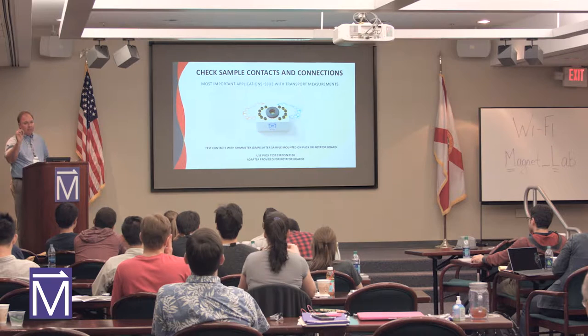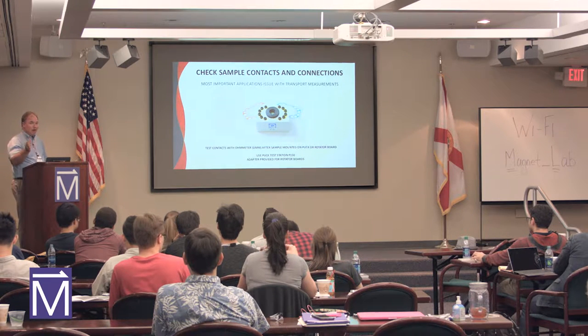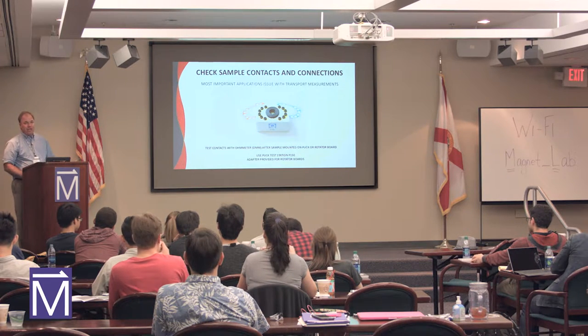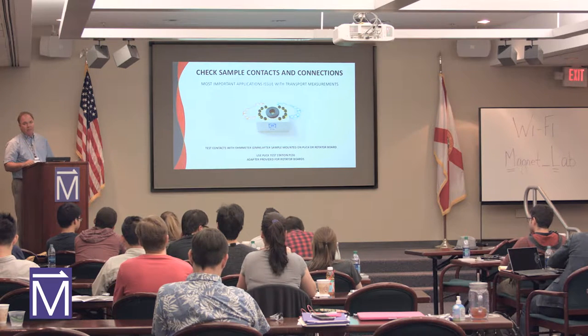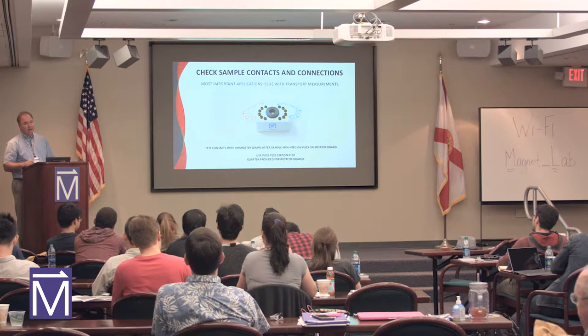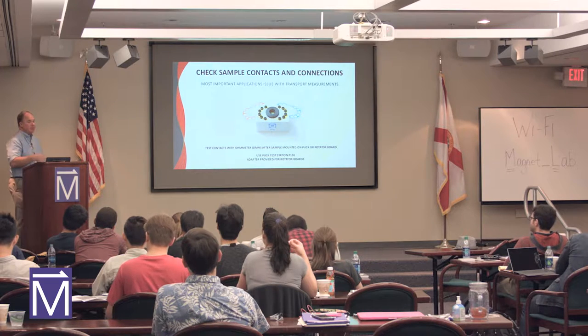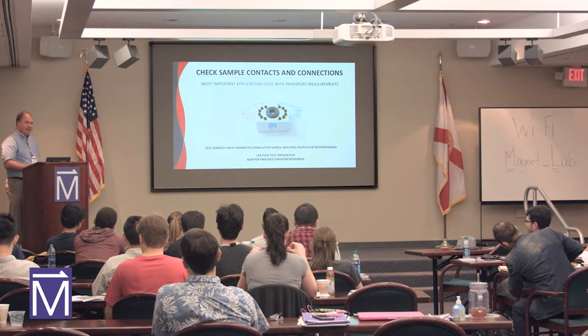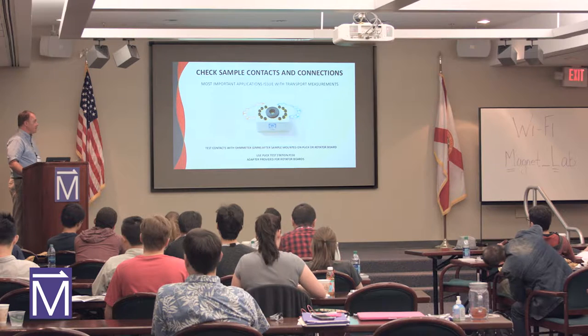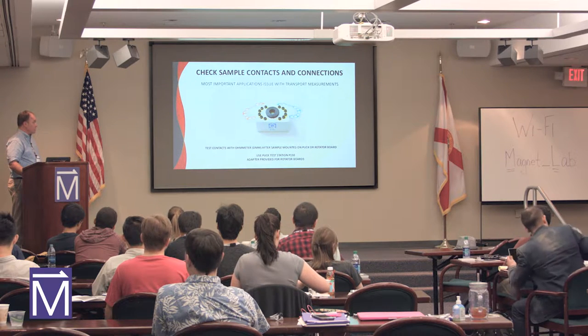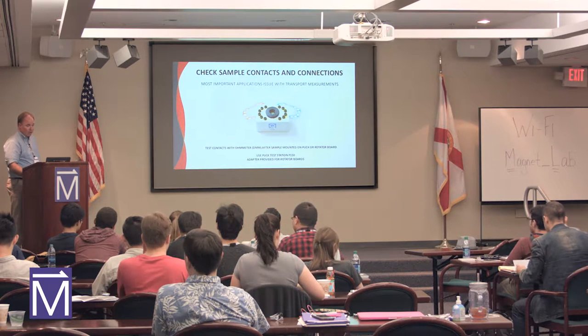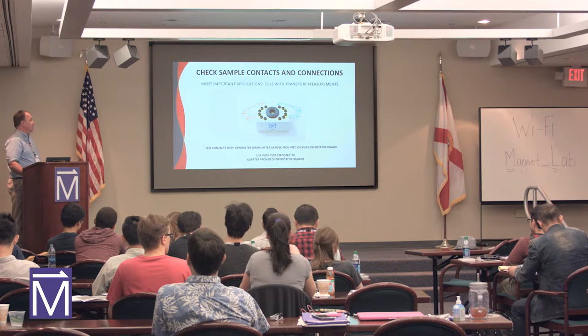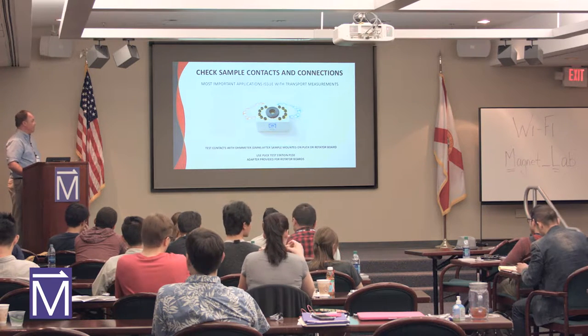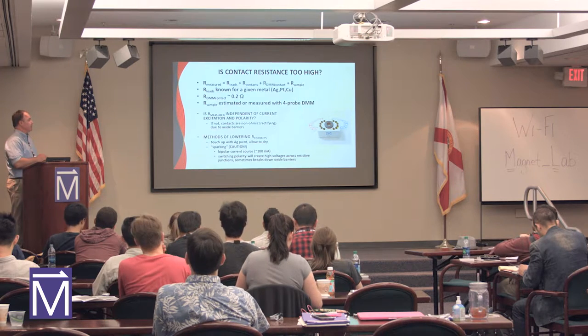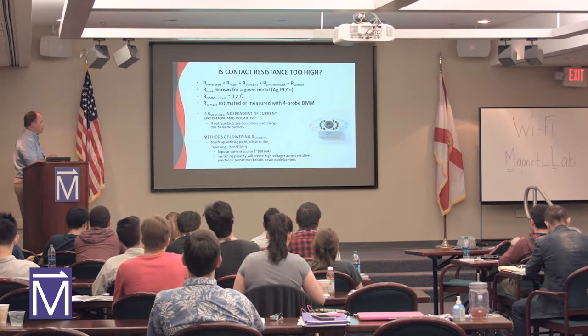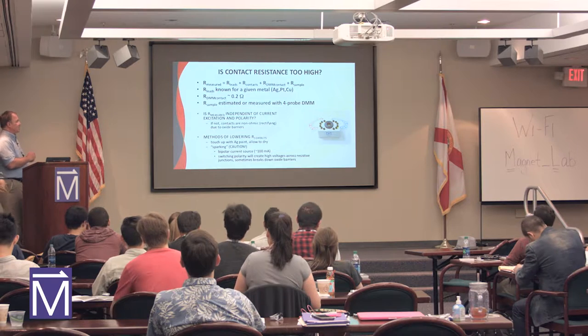So mount your sample on the puck, put it in the measurement jig, and then you can use an ohm meter, multimeter, or Keithley meter to make your electrical contacts at room temperature. Do you have good contacts? And then you can move it into the system. So we give you little kits depending upon the experiment. And if you have the rotator board, it has a little adapter so it fits in the sample holder. There are a couple of little things you can do to make sure the contact resistance is not too high.